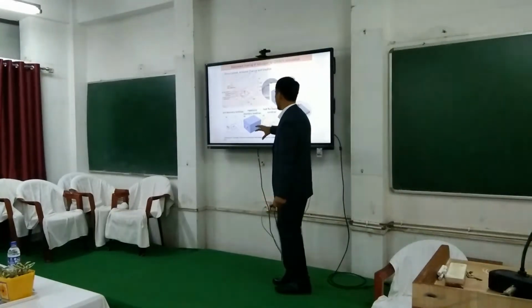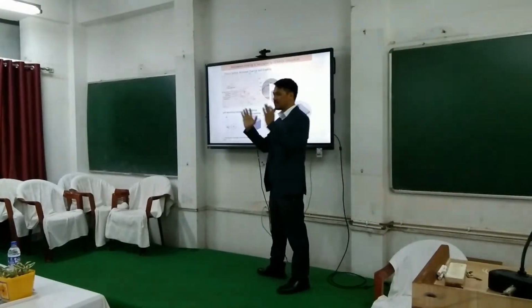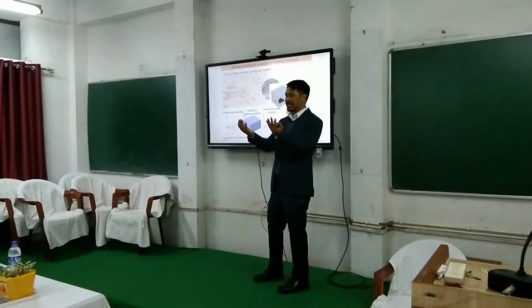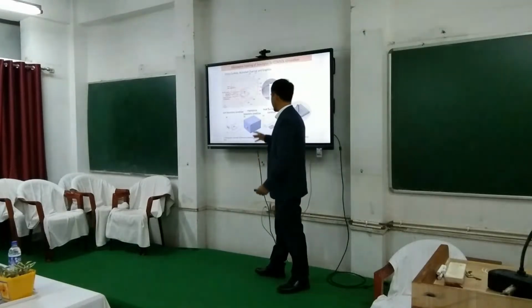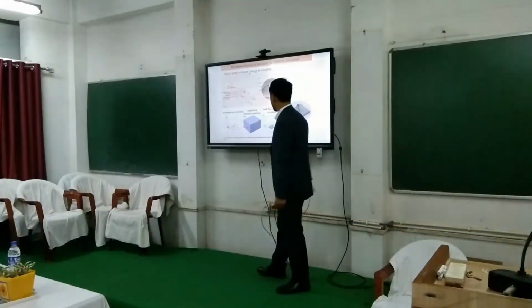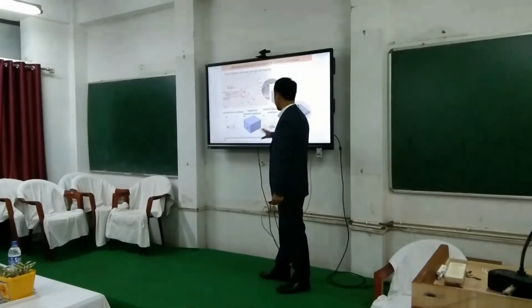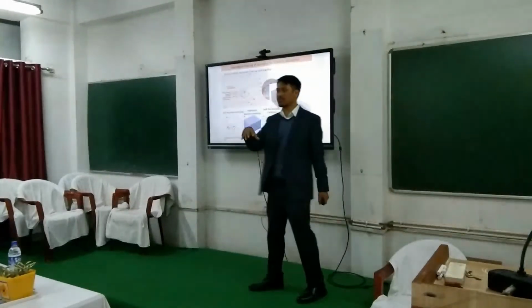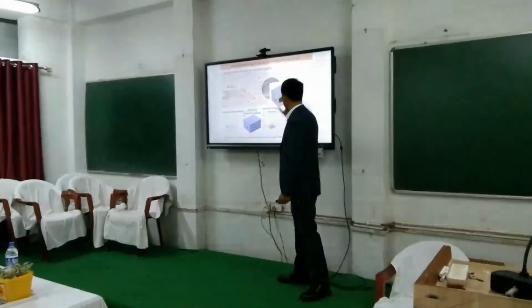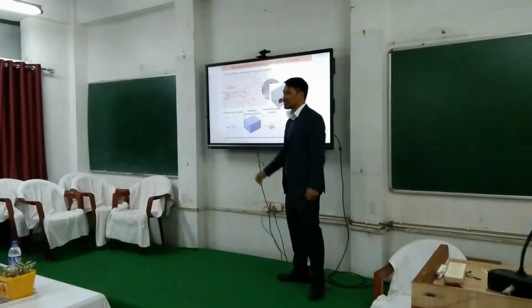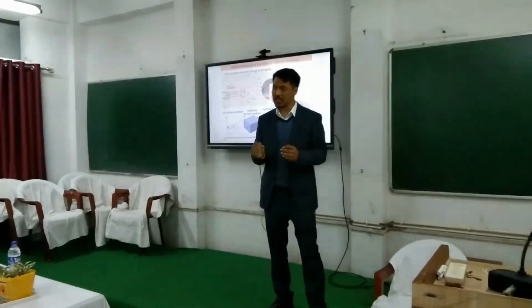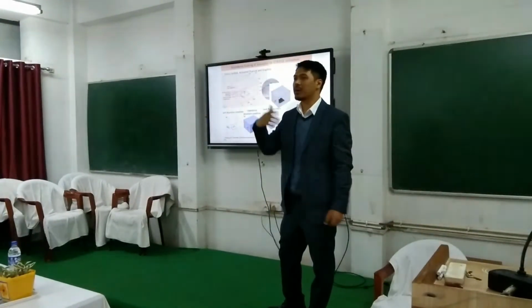So we use a boundary condition in order to show that it is as if it is a metallic wall where microwaves are reflected, which is the impedance boundary condition. With the flux boundary condition, we give in the heat input, whatever you want to heat by the microwaves. We have port boundary conditions which help us to simulate how much microwave energy, what frequency is going into the oven.